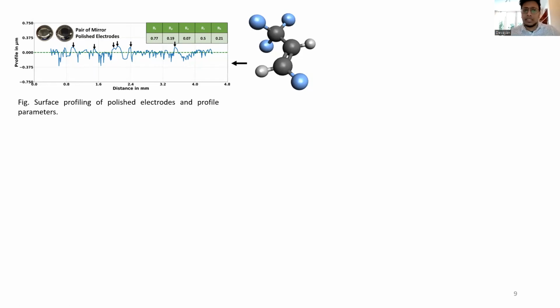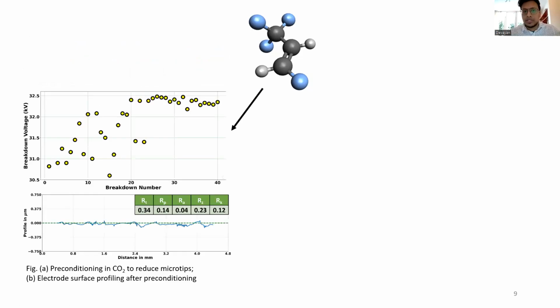And these tips become very sensitive when you go to higher pressures. So we really needed to eliminate the tips. Here comes the CO2 into the picture. We preconditioned our electrodes with initial shots of CO2. Once we did it, we saw that the first few shots in CO2 were very low. Why? Because you had those microtips, which had a field enhancement on top, and that field enhancement reduced the values. But after 20 to 30 shots, the values were super coherent. So you can understand that maybe we got rid of the microtips. You can't quantify it, but we did it at least 50 times, and after 20 to 30 shots, you have a very coherent value.